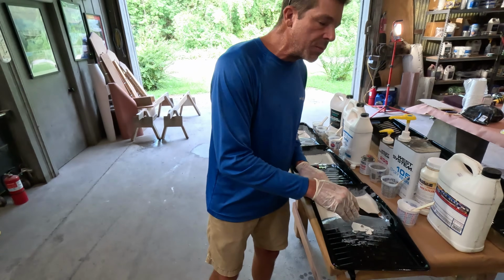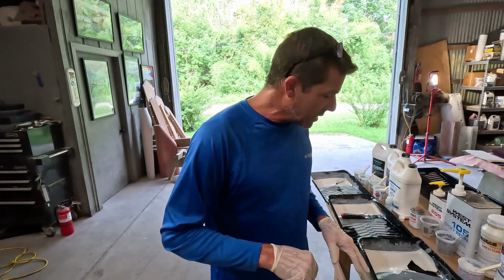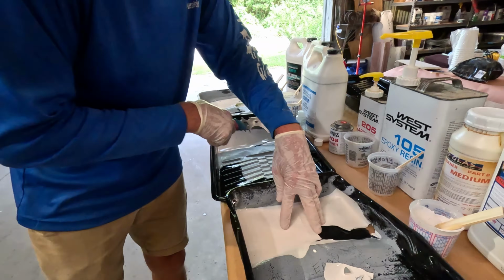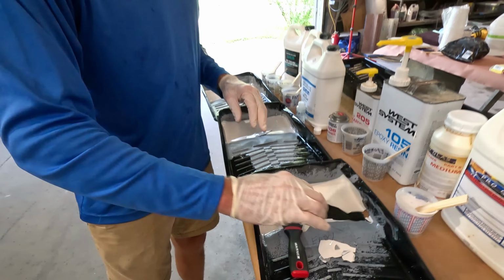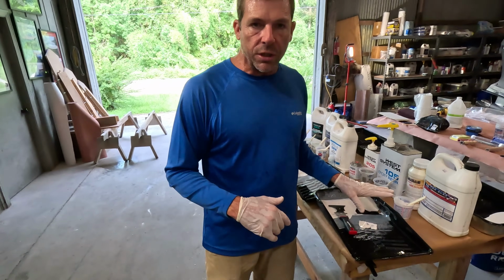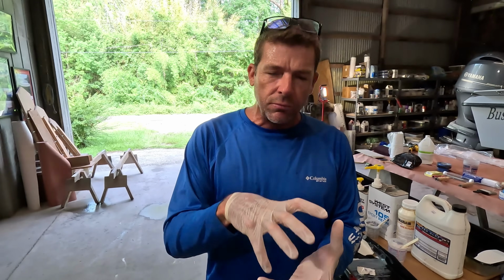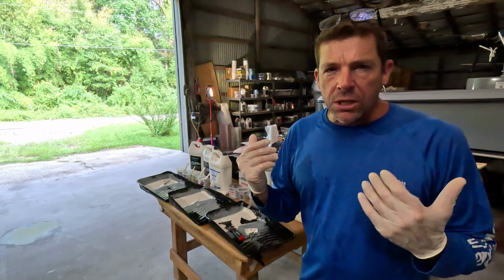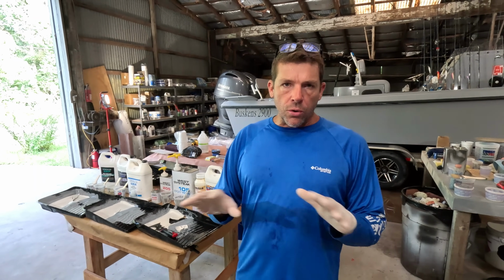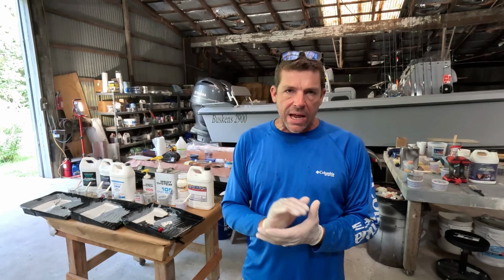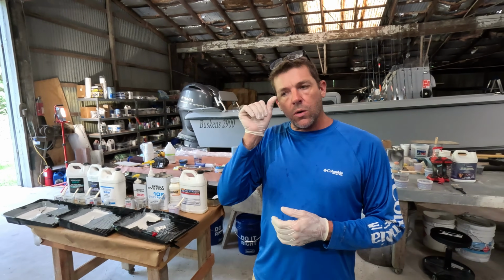So there's so much mystery when you apply gel coat over an epoxy base. A lot of times what happens is, for example, this looks okay. You're like, well, man, it cured. It looks just fine. But in reality, it's not. That is not what you would want on your boat. Even though I blended these two materials together, a lot of times folks may make an epoxy repair and put some gel coat over it. It may initially seem to be fine, but over time it can lose its bond and let go. Or when you initially put it on, sometimes you will basically have no cure. The gel coat remains in a wet state and doesn't ever activate at all. So I generally don't recommend applying gel coat over any kind of epoxy.